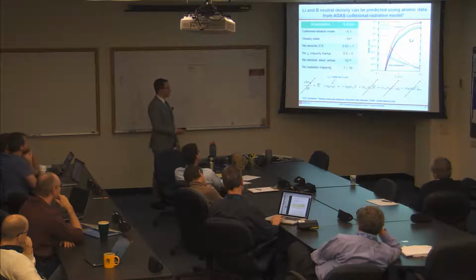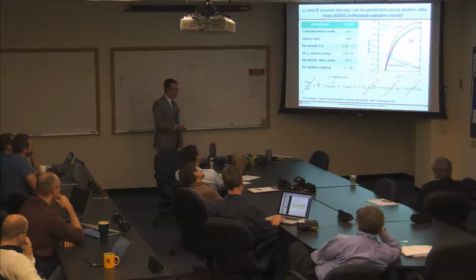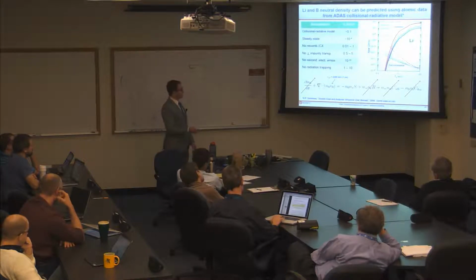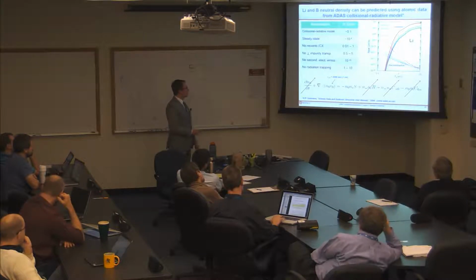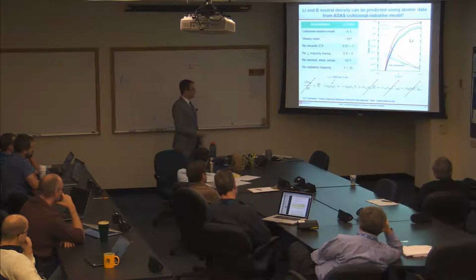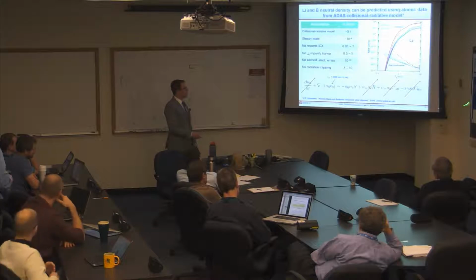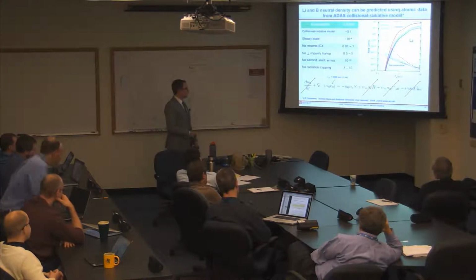And the S and R terms come from the ADAS collisional radiative model, which is an existing database of atomic physics data, atomic physics quantities. And they're plotted here for lithium as a function of density and temperature. As you can see, in the parameter range we're talking about, which is above 1 eV at densities of 10 to the 14, 10 to the 15 per centimeter cubed, the ionization is way higher than the recombination, so you can drop that. The charge exchange terms I haven't shown here. They're actually way off the bottom of this plot, and those are also small.